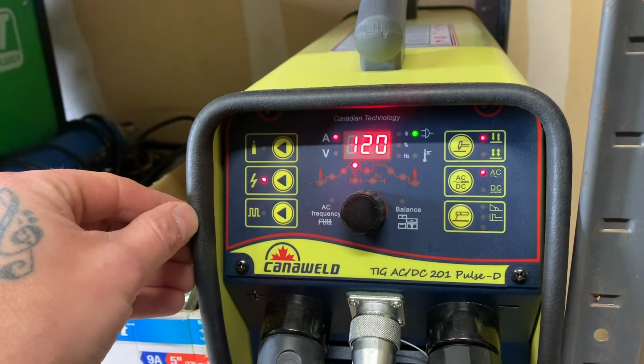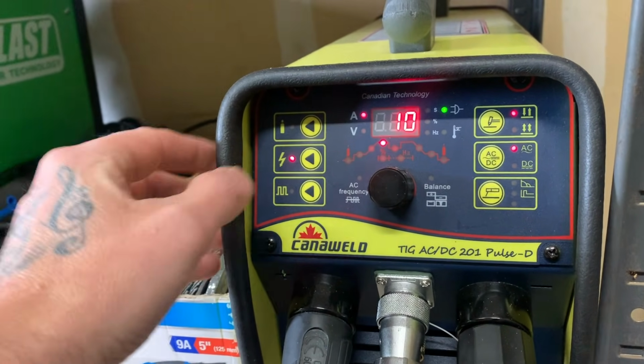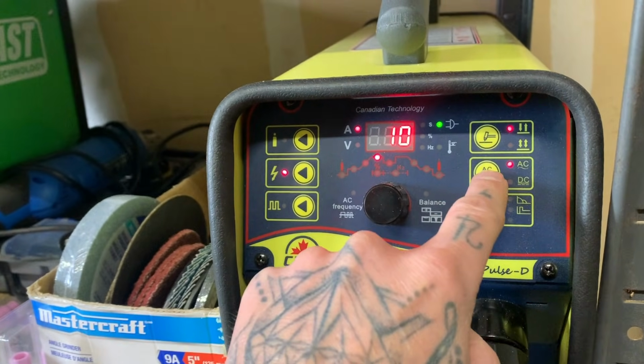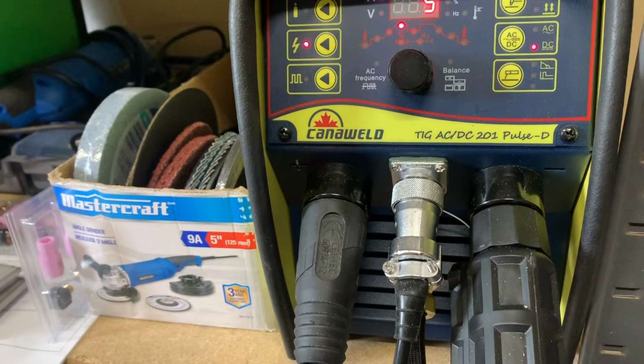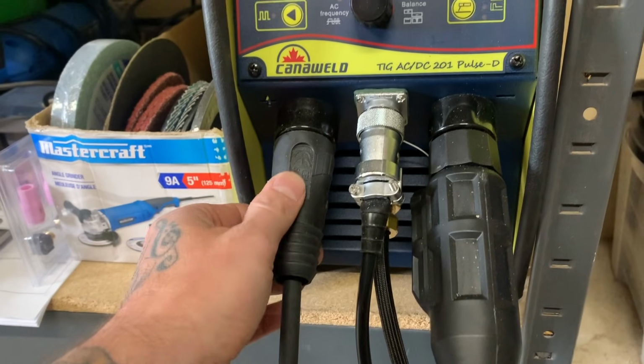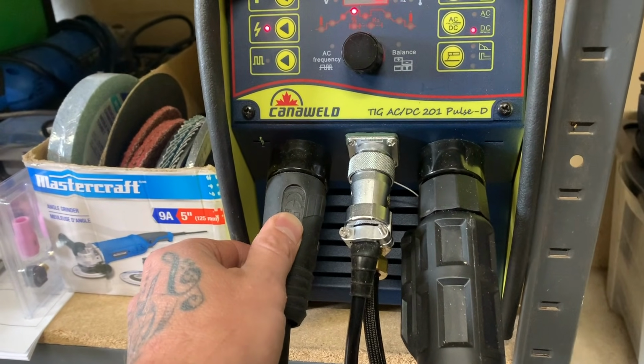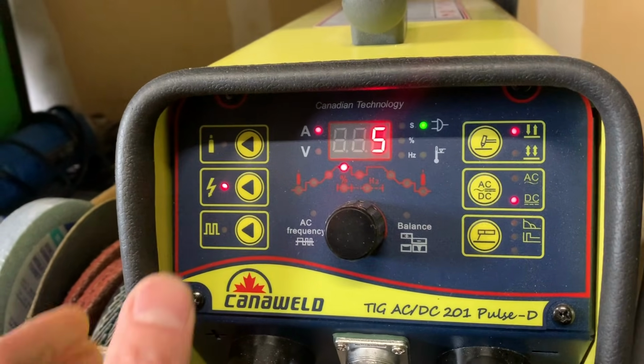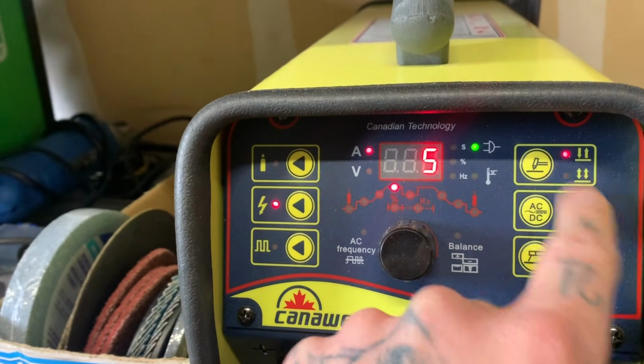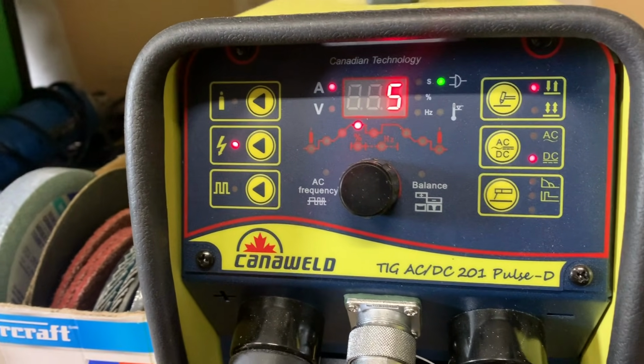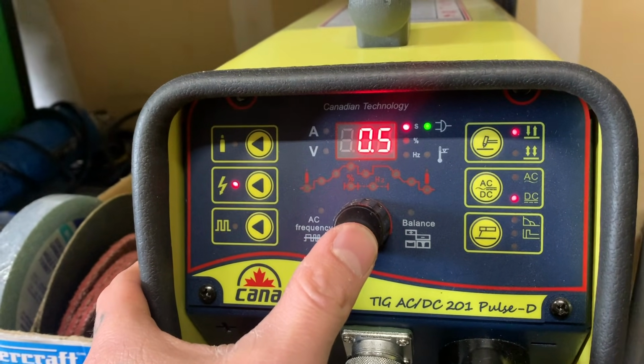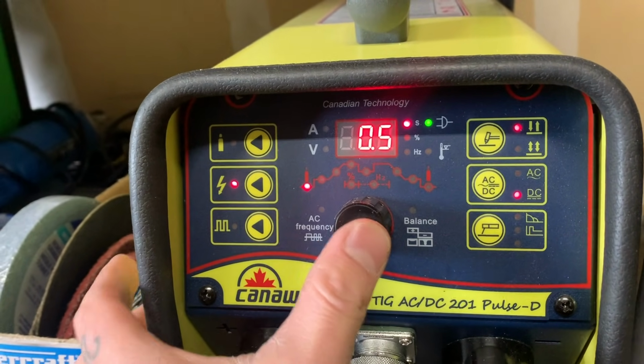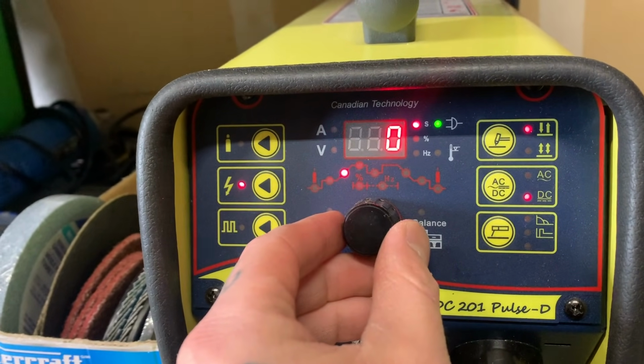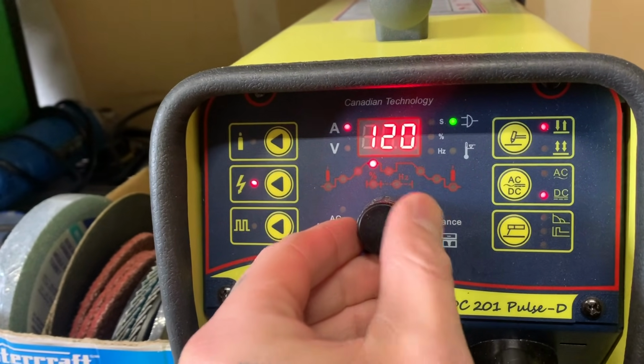All right, so what we're gonna do is set this up for some DC negative welding. So on this guy here, we're gonna switch it over to DC. It's already set up because our torch lead and our ground is set up so that it is gonna be running DC negative. So there's not much we're really gonna set up here. I'm on two-step. Obviously, I'm using a foot pedal. I'm just gonna control it with my foot. First thing we'll see here, I'm running about 1/2 second of pre-flow. That's cool. 0 upslope, don't want any upslope.